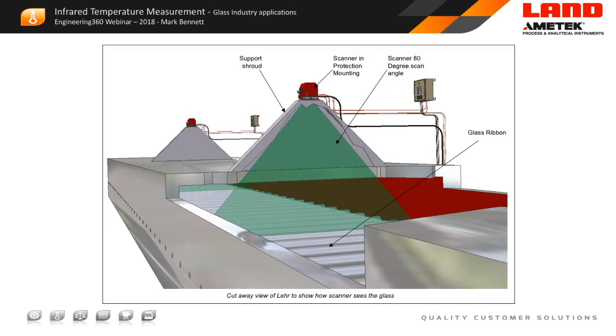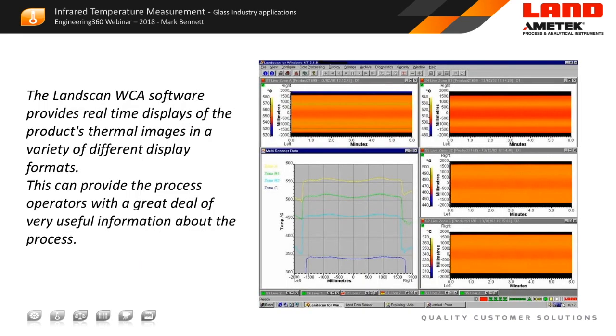Land has a full glass Lehr solution. So we have put together our knowledge over the years to produce a rugged housing that's suitable for mounting on top of the glass Lehr with a sighting cone. The sighting cone here has to seal the gases, and that gives us access to measuring across the full width of the glass. And from that, we use the software to produce what are these thermal maps and temperature profiles, a temperature profile across the glass. So these are critical measurements, critical parameters for any manufacturer of float glass.